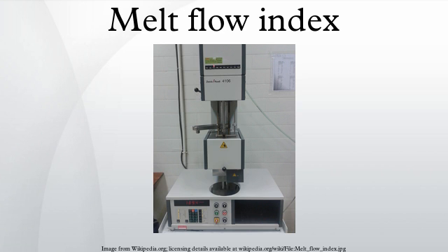A piston is introduced which acts as the medium that causes extrusion of the molten polymer. The sample is preheated for a specified amount of time: 5 minutes at 190°C for polyethylene and 6 minutes at 230°C for polypropylene. After preheating, a specified weight is introduced onto the piston. Examples of standard weights are 2.16 kilograms, 5 kilograms, etc.